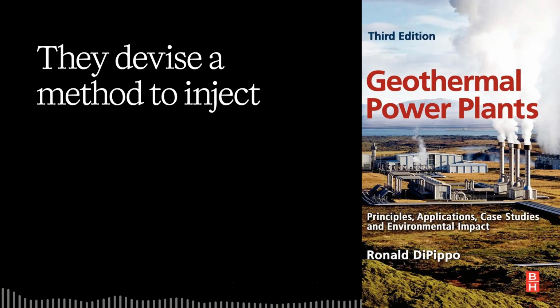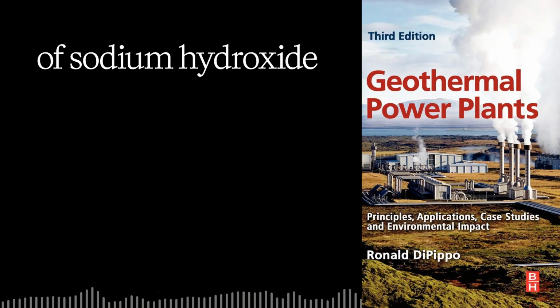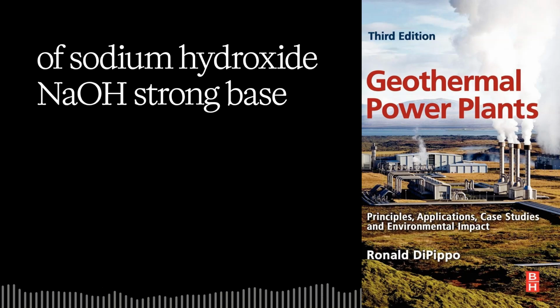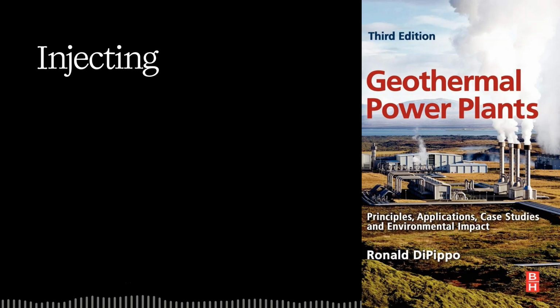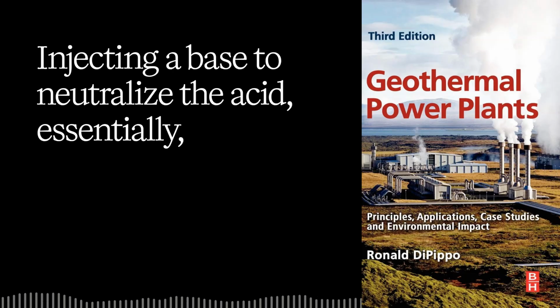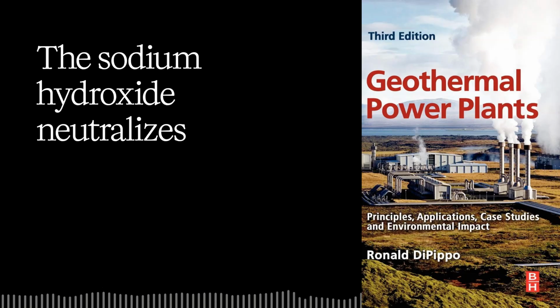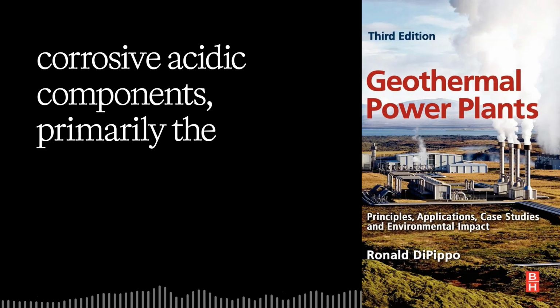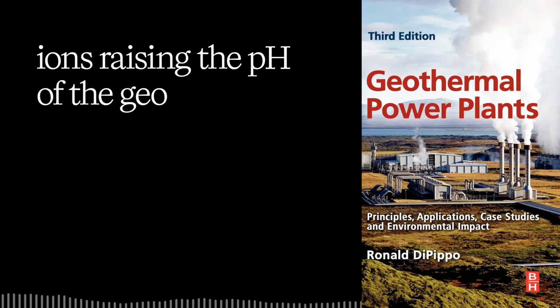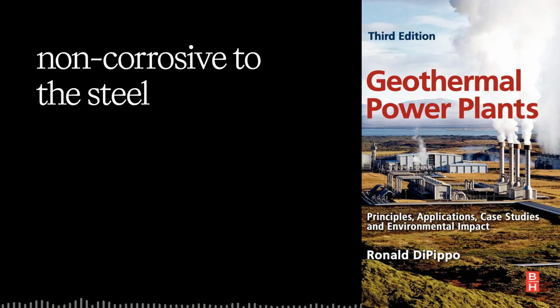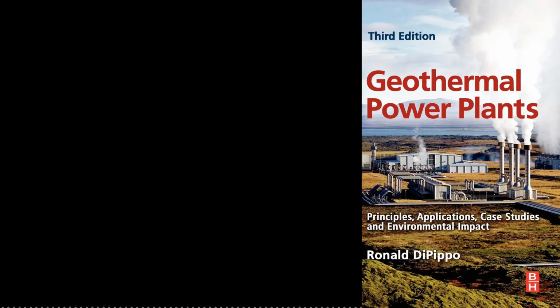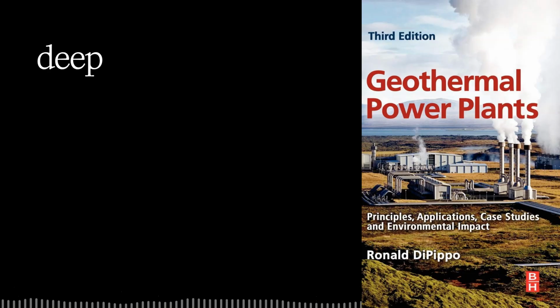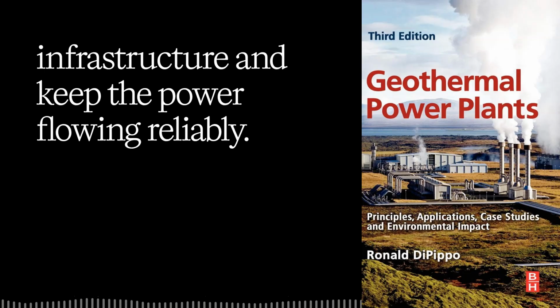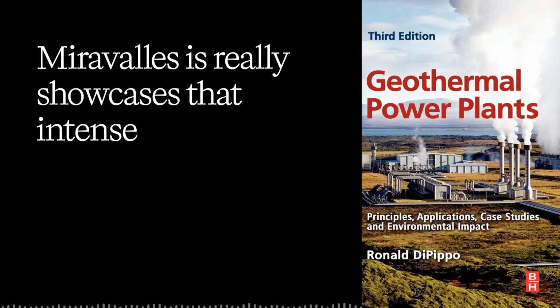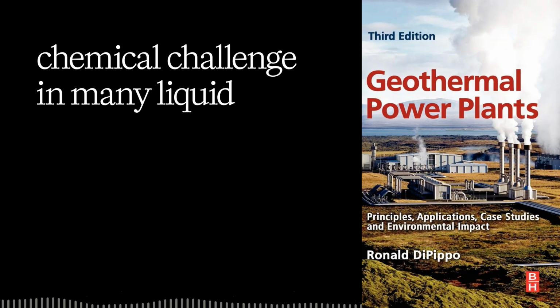They devised a method to inject a very dilute solution of sodium hydroxide, NaOH, a strong base, deep inside the production wells. Injecting a base to neutralize the acid. Essentially, yes. The sodium hydroxide neutralizes the corrosive acidic components, primarily the H+ ions, raising the pH of the geofluid just enough to make it non-corrosive to the steel equipment by the time it reaches the surface. Again, it's about carefully managing the chemistry deep inside the earth to protect the expensive surface infrastructure and keep the power flowing reliably. Miravalles really showcases that intense, ongoing chemical challenge in many liquid-dominated fields.